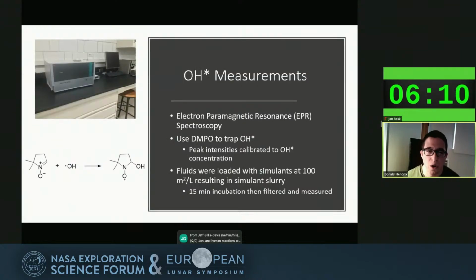We measure OH radical through a technique called electron paramagnetic resonance, or EPR spectroscopy. Basically, we take about 100 meters squared per liter of sample, based on the surface area of the dust simulants, and incubate that in half a milliliter of an organic compound known as DMPO. This is the organic molecule, DMPO, and it will react with any hydroxyl radical generated in solution by any of the three simulants. That forms a stable organic radical compound, which can then be measured very easily using the EPR. We can't measure OH radical directly because it is very reactive, so we have to trap it, and that's what the DMPO does.